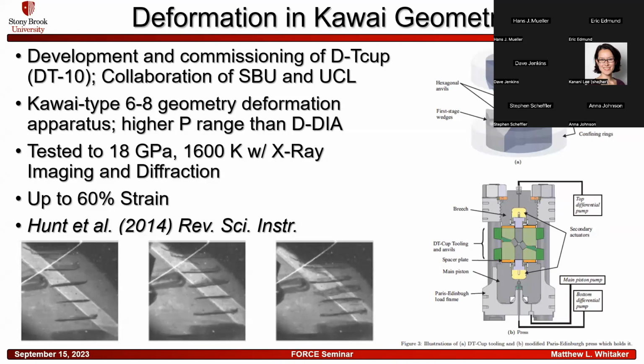As you can see with the X-radiographs shown at the lower left, as you move from the left to the middle to the right, that's increasing the amount of strain on the samples. So we were able to shrink the whole thing by 60%. And this was something that we had commissioned and published just before NSLS-I shut its doors in 2014.